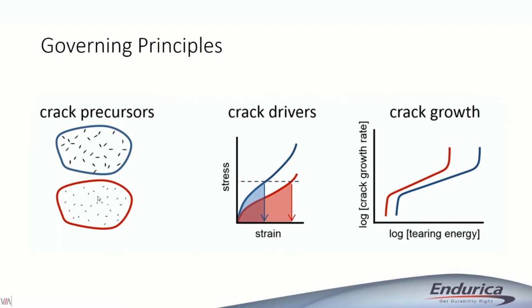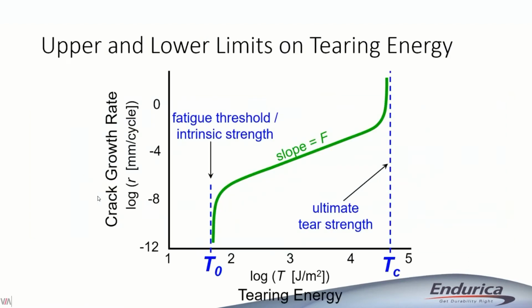And if it is, how fast does it grow? So these are the big questions that all of these approaches are founded on. Now, if you look specifically at the crack growth rate curve for an elastomeric material, this chart here shows the typical behavior that we observe over a very wide range of rates. A couple of important features on this curve.